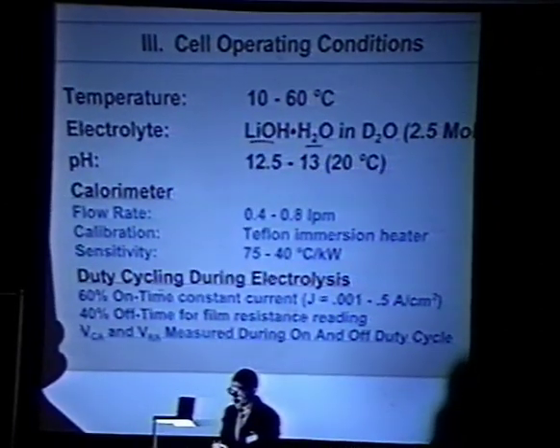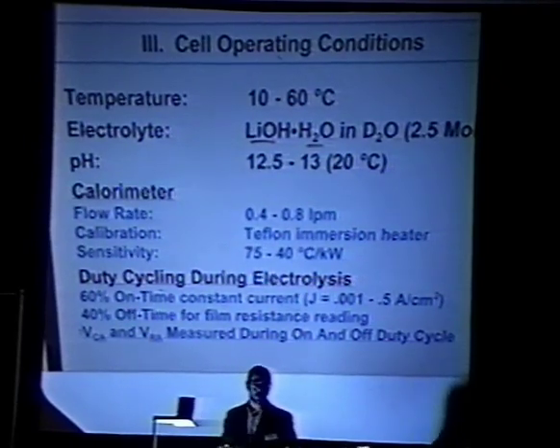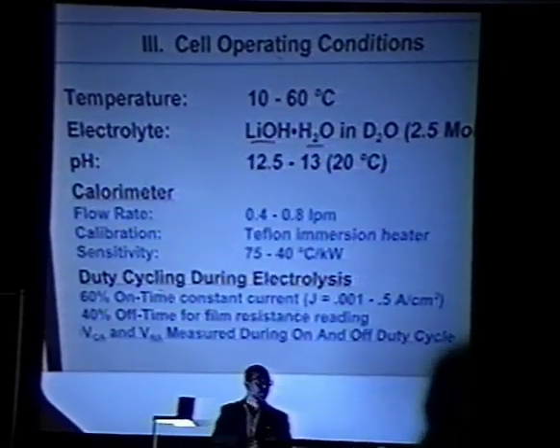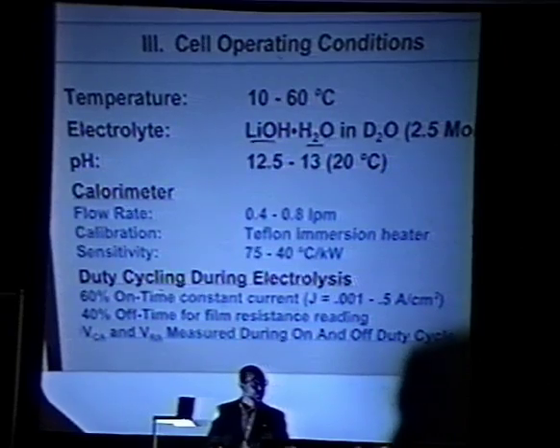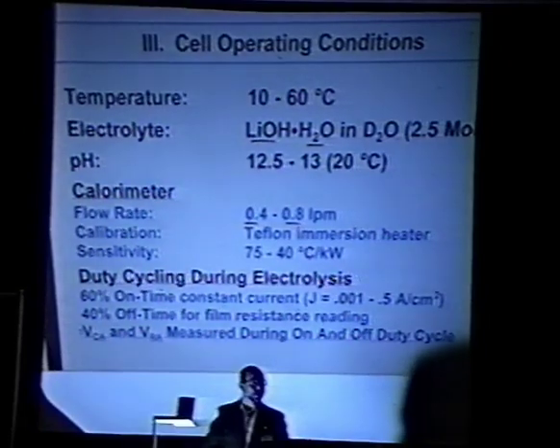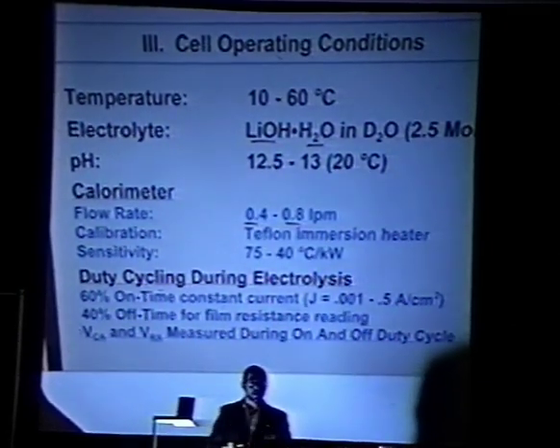Now the calorimeter itself, it actually can run anywhere from about 0.2 liters per minute up to about 3 liters per minute. But the data I'm going to show today is in this range. It's basically 0.4 and 0.8 liters per minute. And it gives me a calibration sensitivity. Well, the calibration is done with a Teflon immersion heater. Just put an immersion heater in there and keep track of the power in, power out, and calibrate the thing.